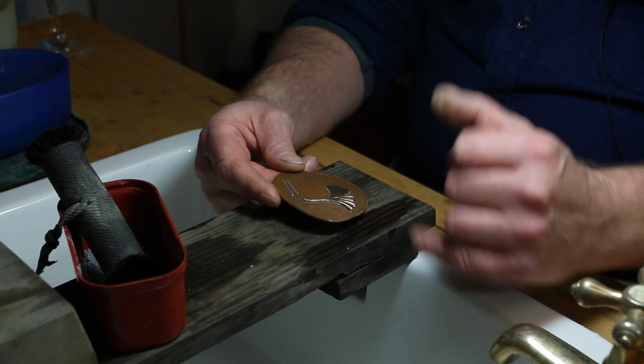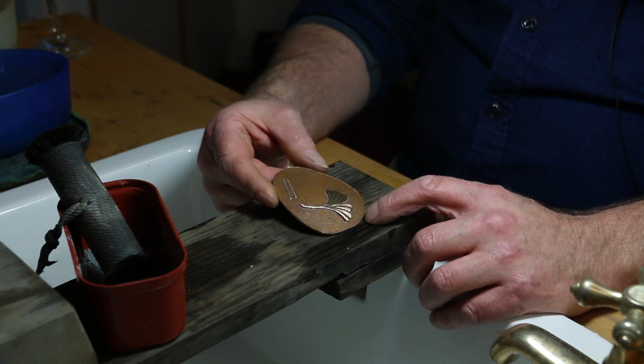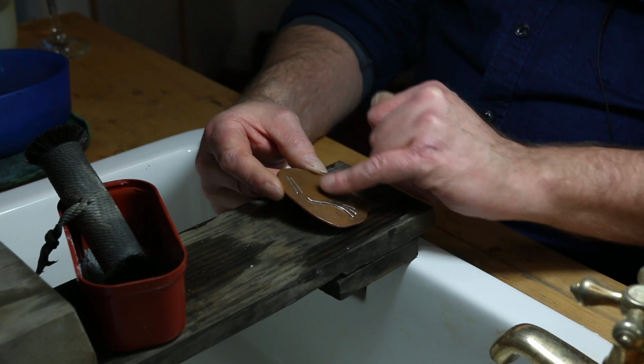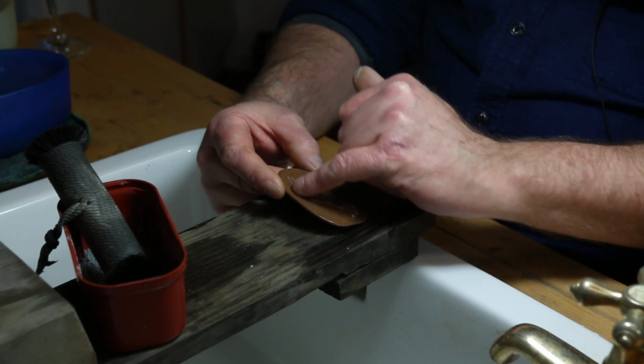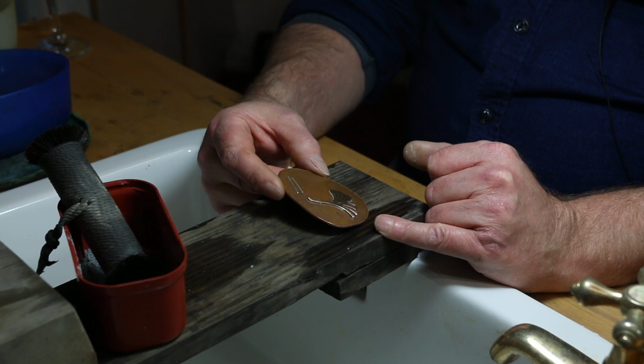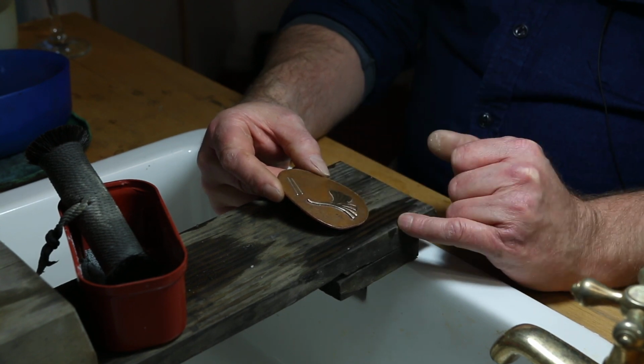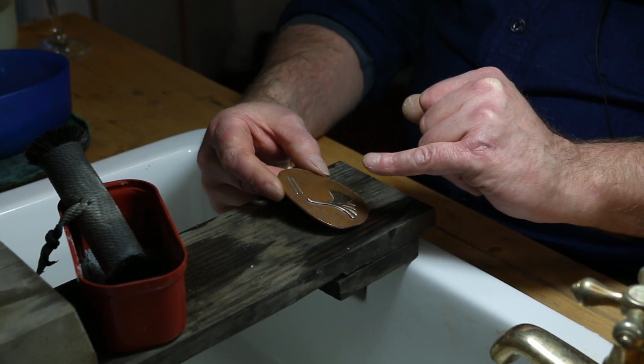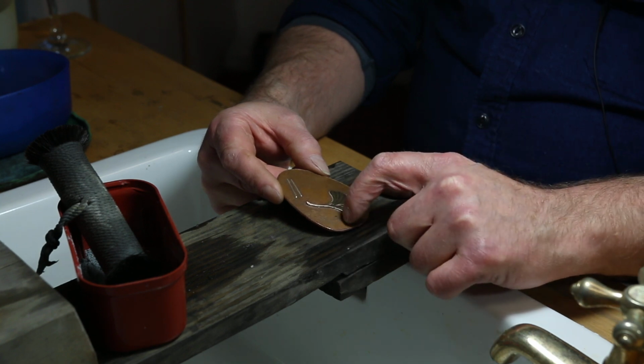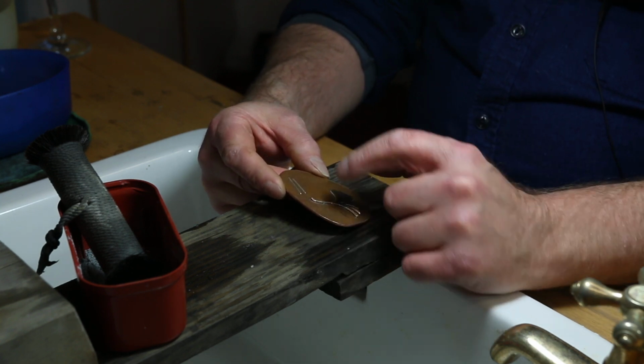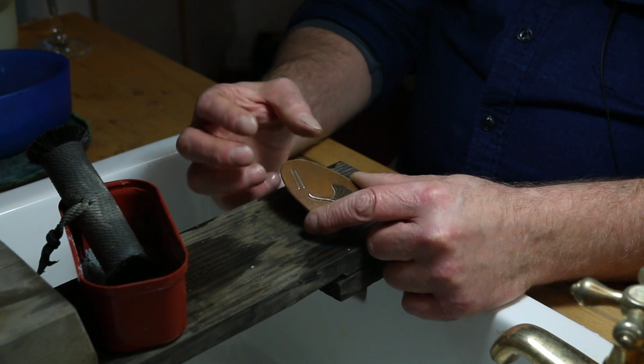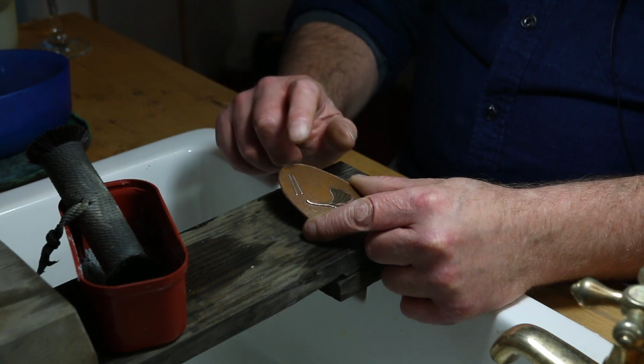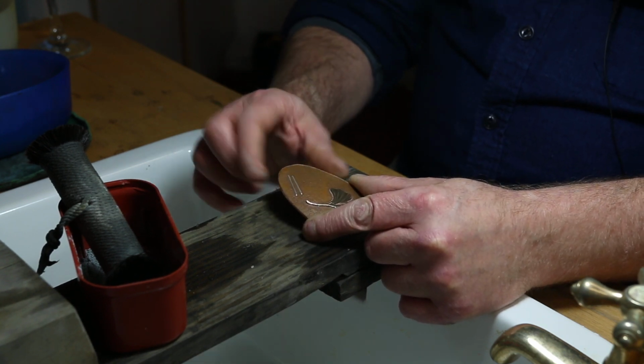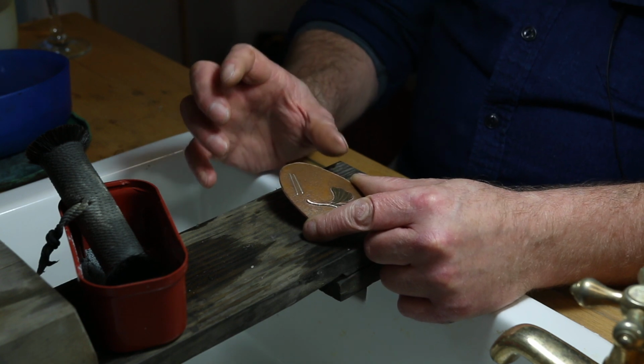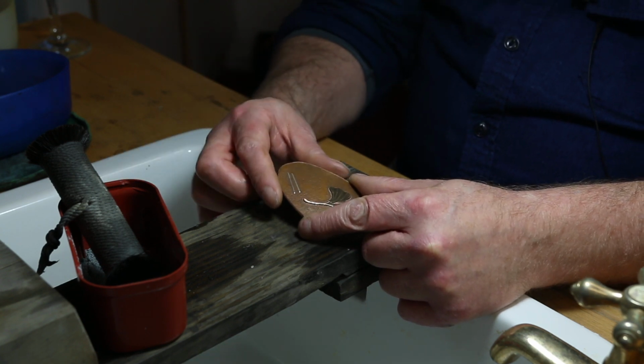It's a partially completed exercise from a class. It's got a rough texture. It's got some smooth spots. And it's got two strips of silver inlaid. The silver is quite important to us because I maintain if you can patinate copper really well and get a good color in copper without the silver going yellow, then chances are you have a good understanding, good control of the patinating process.